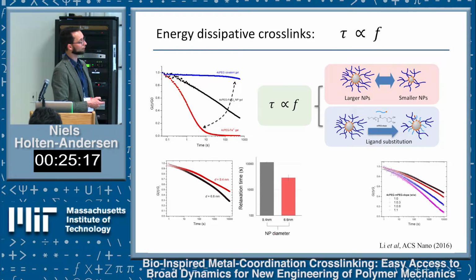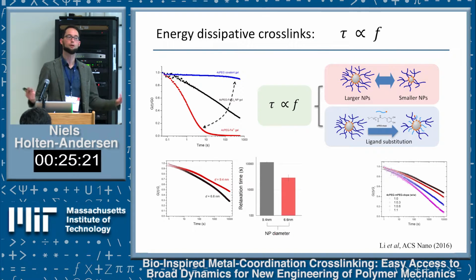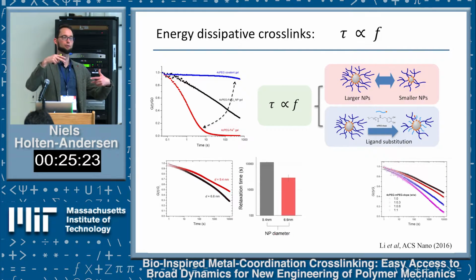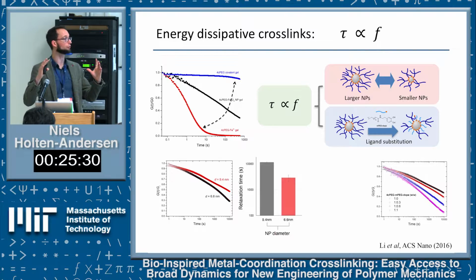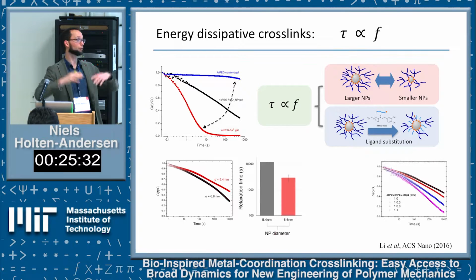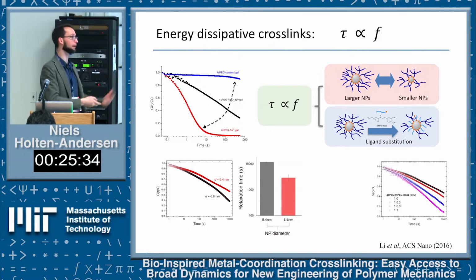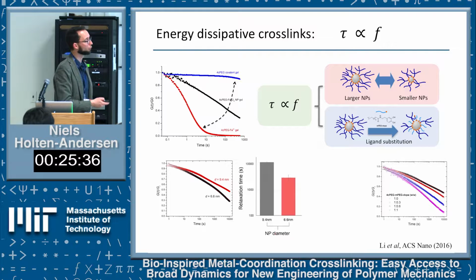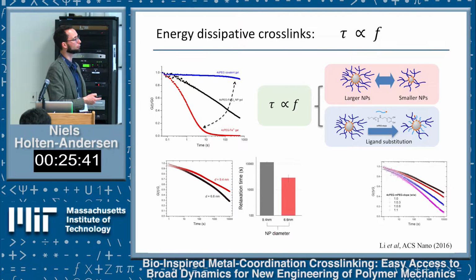An even simpler trick, instead of changing your particles, is to add free ligands to the network. You begin to bind the particle with ligands that won't contribute to the elasticity of the material. You're crowding out the stress-bearing crosslinks per particle, forcing them off, and making the network more fluid-like. And that works even more simply—without engineering the material composition of your network, you just add more of these small molecules, and you can engineer it down into a fluid or back up into a solid very easily.